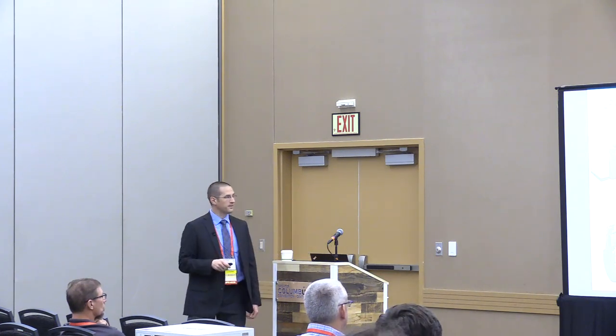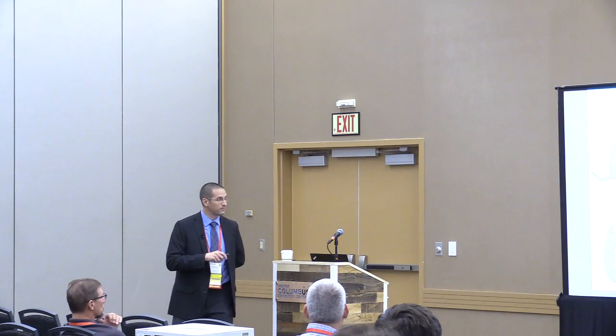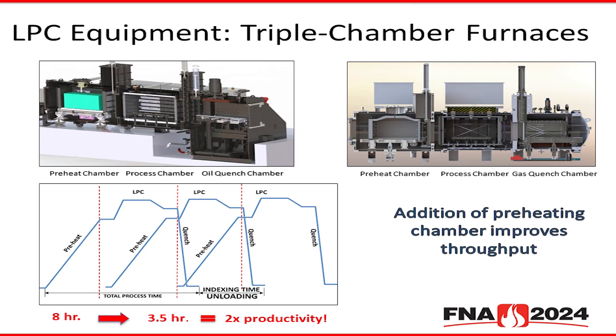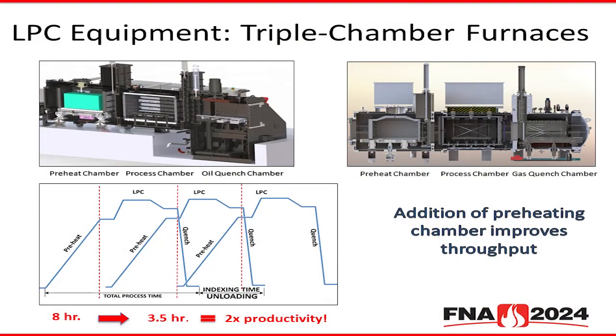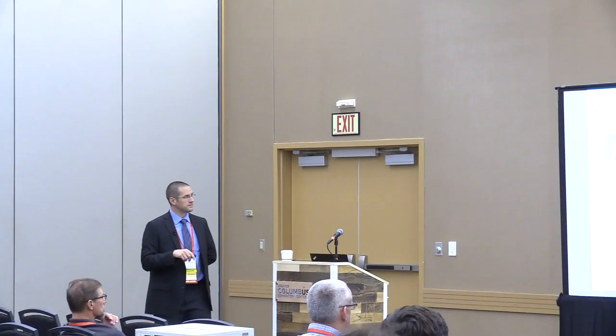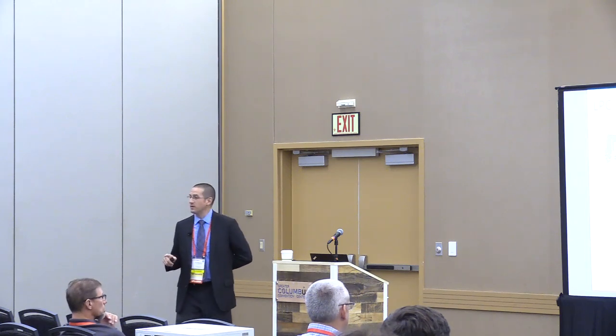If this configuration, or excuse me, a two-chamber furnace doesn't produce the required cycle time, we also have another option, and that is a triple chamber furnace. The advantage here is, again, we can do both gas and oil quenching configurations, but you'll note the addition of the preheating chamber here. What this does is it allows us to take advantage of the time that we would lose in heating the part in the process chamber, the center chamber here. That ends up giving us almost a 2-time productivity increase over the alternative, which improves the overall throughput of the process. So again, this is for high production rates and allows us to improve our overall capacity.